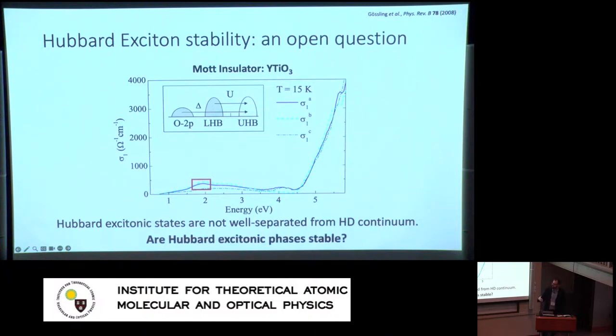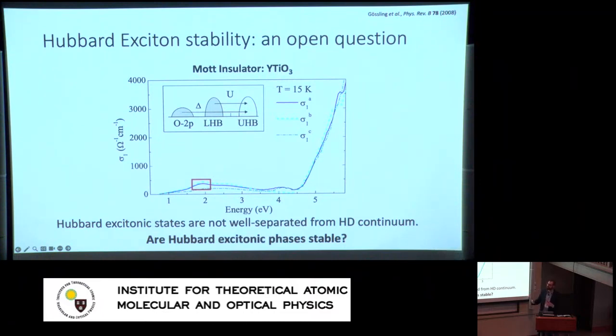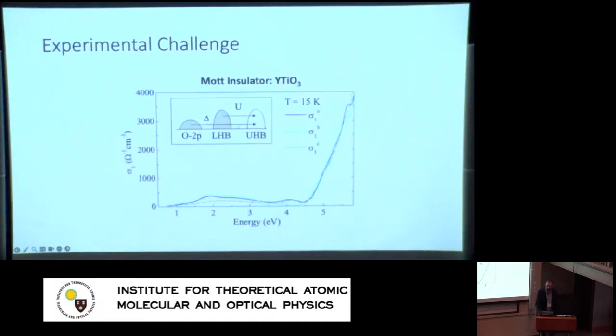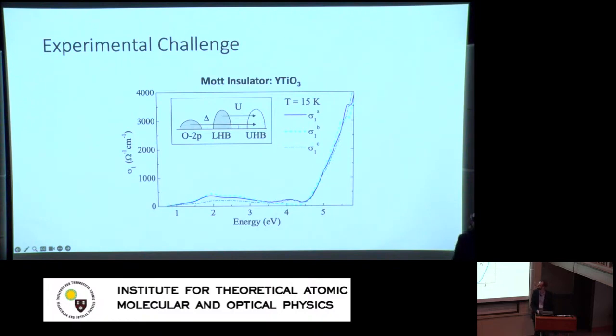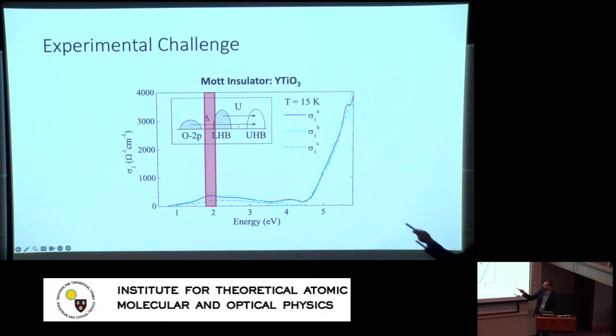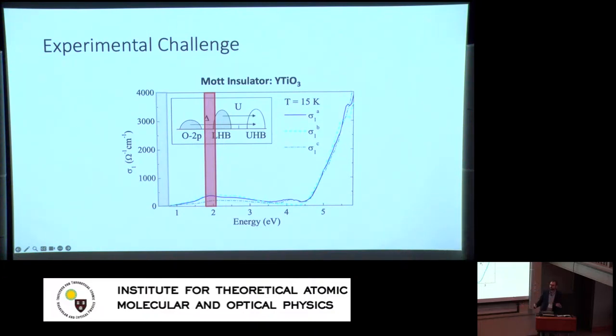In the photo-excited state, you may ask: is it stable for excitons to form, do they contribute to the dynamics, or can we ignore them? The experimental challenge is that to answer this question you want to independently study free carrier dynamics and bound carrier dynamics. But if they spectrally overlap, there's no way of distinguishing whether what you're seeing in a pump-probe reflectivity measurement is from free carriers or bound carriers. What I'm going to show in the rest of the talk is that there's actually a way to distinguish between these dynamics in the terahertz regime, where there's no spectral weight overlap.